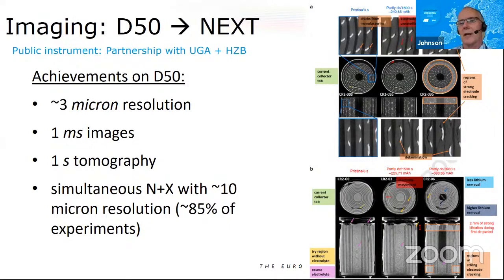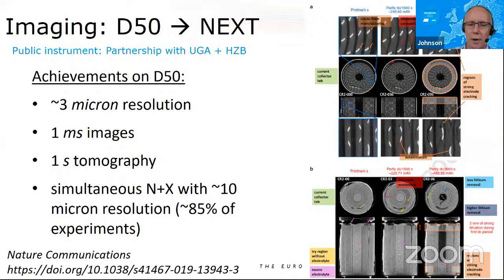This is quite a complex set of plots, but the upper plots come from X-ray imaging, and the lower plots from neutron imaging. And the first thing to note simply is the contrast in the two cases is completely different. And essentially, the simple message is that X-ray imaging sees the electrodes and neutron imaging sees the electrolyte, i.e. the lithium. And one very simple thing to notice here is that here in the center of the battery, you see electrolyte depletion as a result of the cycling of the battery. And of course, there's many fine details that can be extracted from this data. And this work was published not so long ago in Nature Communications.